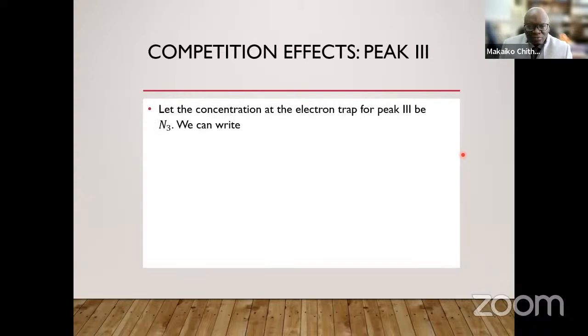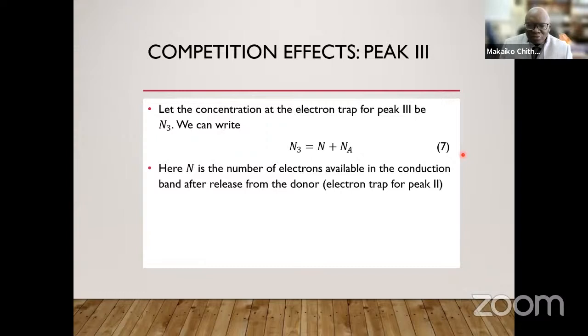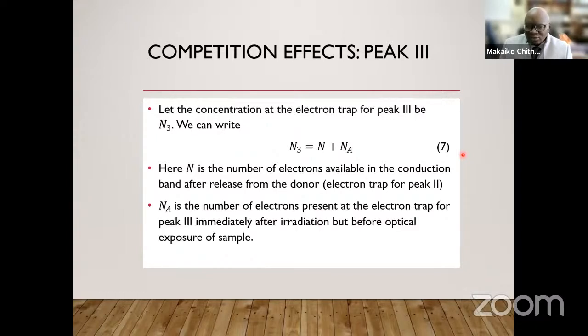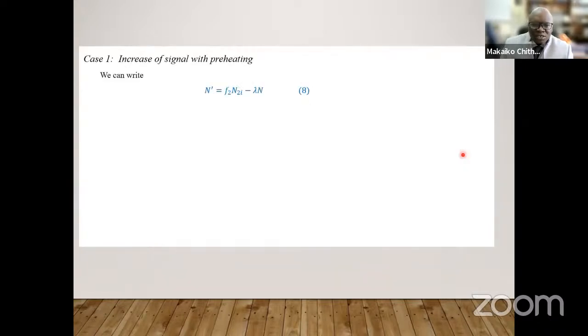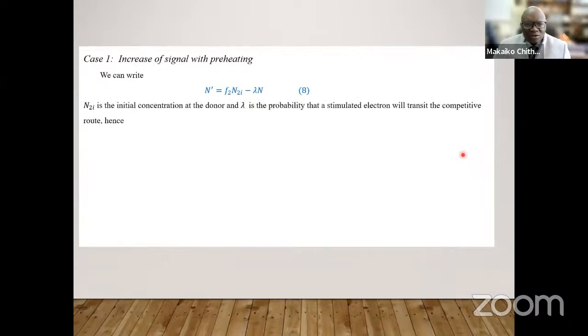The other point I showed is the competition effects for peak 3, where the electron trap for peak 3 seemed to act like a competitor. So in this case, you can write the concentration to be N3, where N3 is N plus NA, and N is the number of electrons available in the conduction band. NA is the number of electrons immediately after irradiation, and NA will be a constant. The increase in signal can be expressed in that way, because this is the number that you are getting from the donor minus the number that transits to the competitive route. So the solution to that form is equation 9.